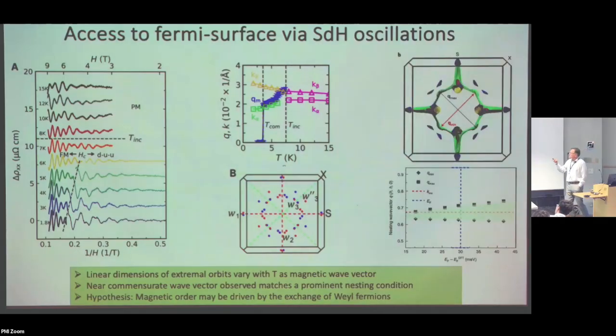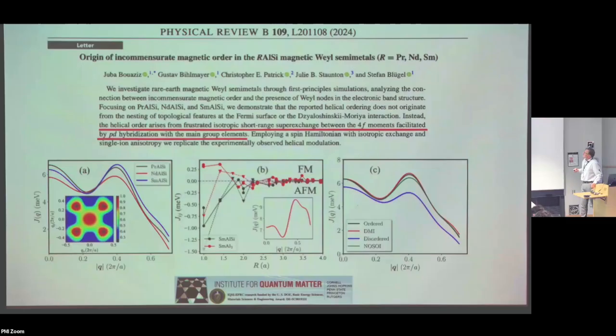And then to make more strongly the connection between the calculated band structure and the magnetism, I have this plot here, which shows, as a function of the chemical potential, which is, as I said, not well determined in DFT, these two wave vectors that I had shown on this chart here, the minimum and the maximum wave vector. And the observed experimental wave vector is this dashed line here. At the point where that one sort of splits the difference between those two nesting wave vectors, that's how we determine what the chemical potential actually is in the system. So we think that we have a case that the magnetic order and its periodicity is driven by the particular nature of the Fermi surface in the system.